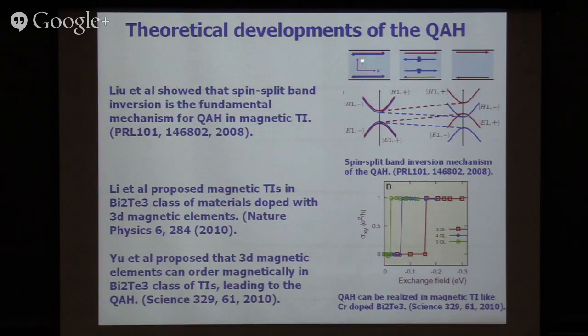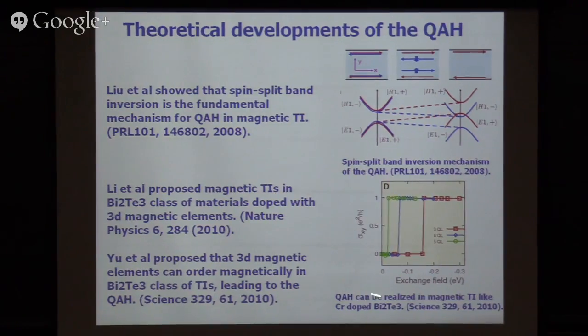quantization. Another picture to see it is that if you have states going forward and backward in a quantum spin Hall effect, but now if you put in a magnetic moment which breaks time reversal symmetry, then it will annihilate one pair of the states, leaving only one chiral branch intact. So there's a natural evolution: when you dope a topological insulator, whether it's 2D or 3D, by magnetic elements, it will actually form a two-dimensional quantum anomalous Hall state, which carries the chiral edge currents without any external magnetic field. And we actually predicted concrete materials; we proposed chromium doped bismuth telluride.